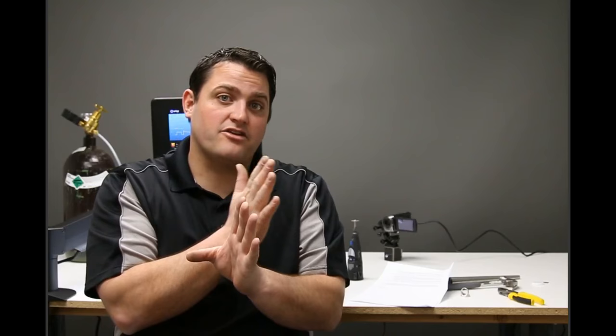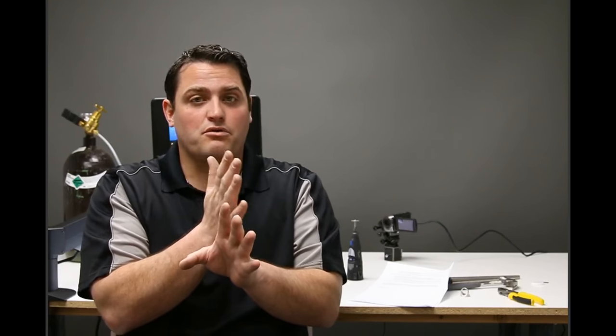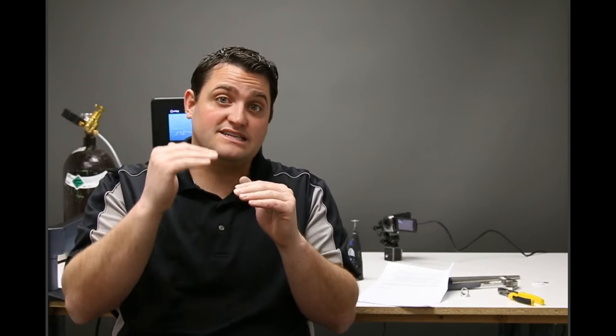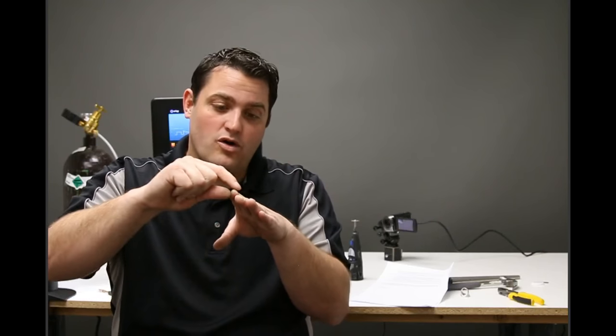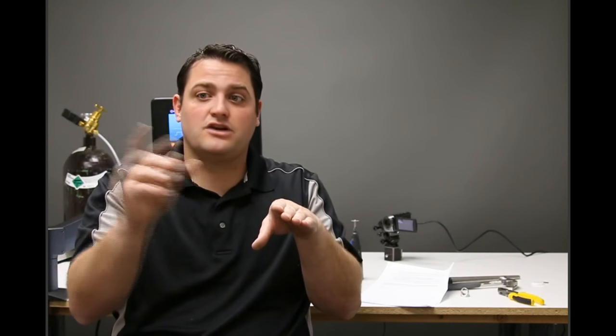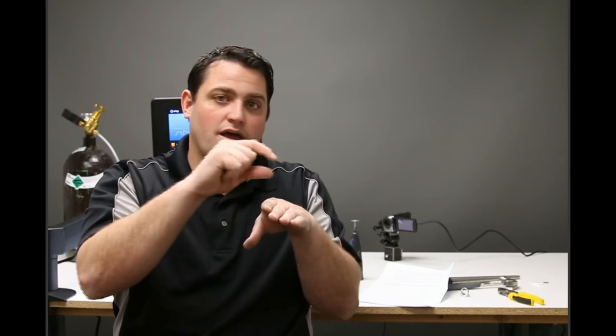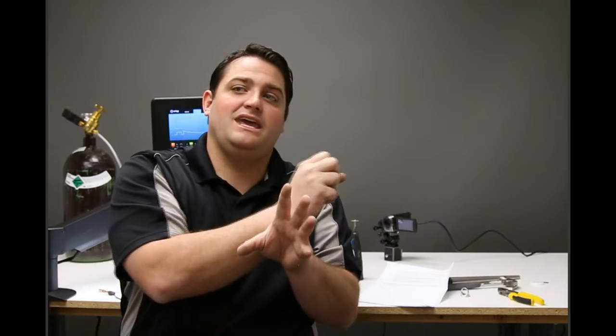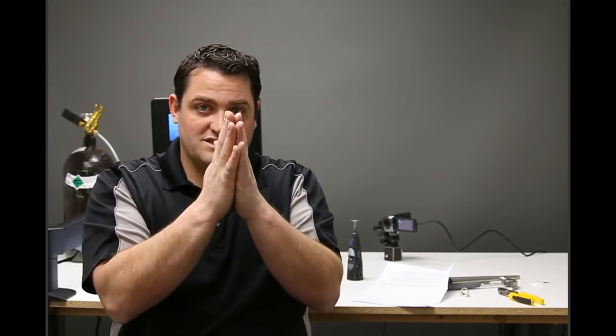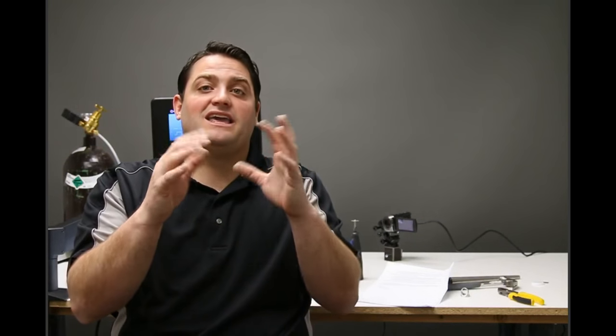Now, we don't necessarily need to be using 100% of the power in the center of that joint. What we want to do is feather it out. We want to bring that energy down and step weld as we go out and do a row here. At this energy, lower my energy just a little bit. Weld it again, lower the energy. What we're trying to do is taper that heat back. So we're spreading from a single line and spreading that heat transfer over that piece. And that can help you a lot with heat cracking. And that works with a laser as well.